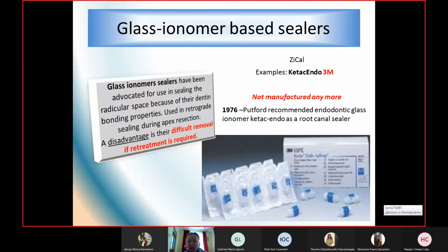Glass ionomer sealers. They were introduced at the same time when glass ionomers were introduced for restorative purposes. In 1976, Pitt Ford recommended an endodontic glass ionomer sealer named Ketac Endo, from the company 3M, as a root canal sealer. But despite its positive qualities, it has a very great disadvantage that overlaps them. It is difficult to do retreatment. This material was not soluble in any solvents. That's why nowadays this material is not manufactured anymore. Glass ionomers are basically rarely used as sealers.